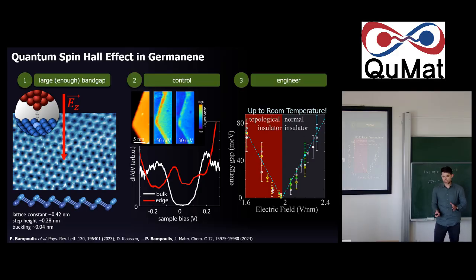So I would say we have a very nice system to study new physics here with a large enough band gap. You can see from this dI/dV curve over here that our band gap is in the range of 50 to 100 meV. We also have control, so we can switch it between a topological and trivial state. And as I will show you in the rest of my talk today, it's a system that allows you to further engineer it and access new states of matter.